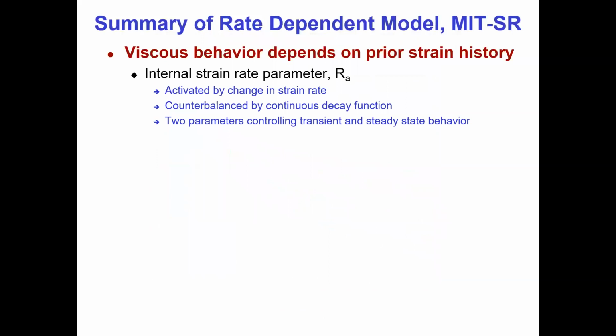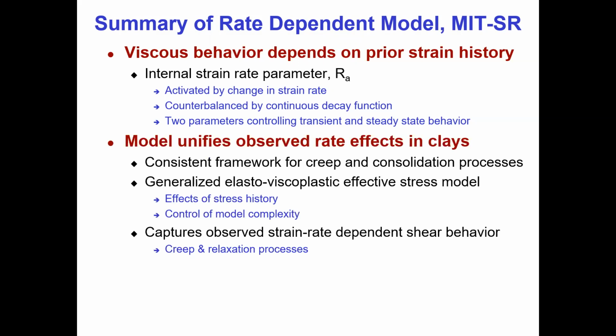So where are we at with this piece of work? What I've shown you is that we can capture this viscous behavior of clays with all their different ramifications through a parameter that depends on the prior strain history, this internal strain rate parameter RA, which is activated by the strain rate, counterbalanced by decay, and you can see how we can describe transient and steady state behavior. The model unifies all of the contradictory observations.